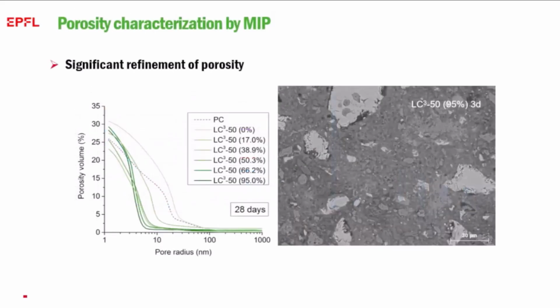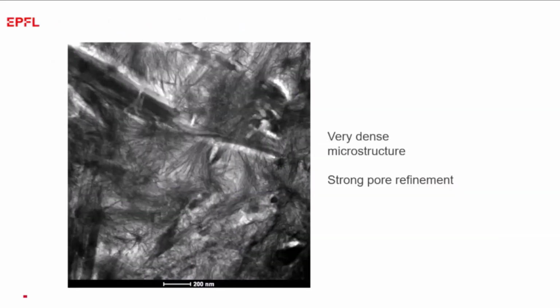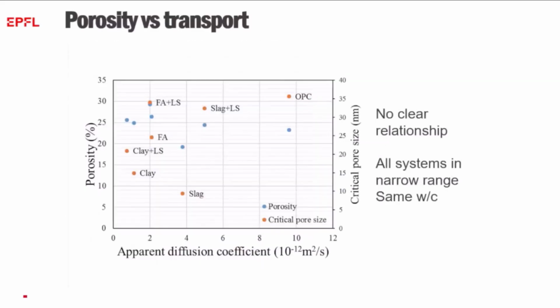Now, when we first started working on this, we thought it was all to do with the pore structure refinement. We can see the mercury intrusion porosimetry curves for the calcined clay mixtures have much finer pore sizes than those for the Portland cement. And even by transmission electron microscopy, we can see this very dense structure given by the C-S-H. In fact, when we studied these 6 blends in more detail, we see it's really rather difficult to draw conclusions, because here we looked at porosity versus transport, both in terms of total porosity and the critical pore size, and we see no particular correlation between them.